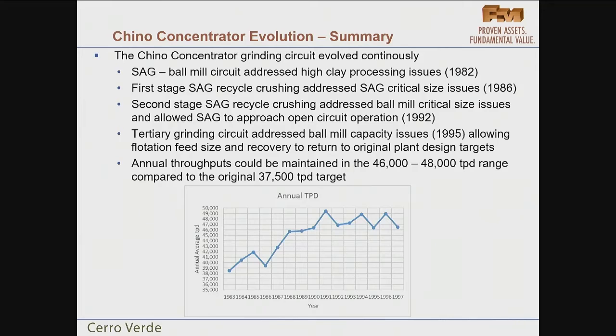So to summarize the Chino activities, very continuous evolution of the grinding circuit. In '82, the original SAG and ball mills addressed the clays pretty well. The first stage crushing plant in '86 addressed SAG mill critical size issues. The second stage crushing plant fixed ball mill critical size issues and allowed the SAG mill to operate in open circuit. We corrected the ball mill capacity issues with the Verti mills, and the whole process allowed performance in the 46 to 48,000 tons a day compared to the original 37,000.